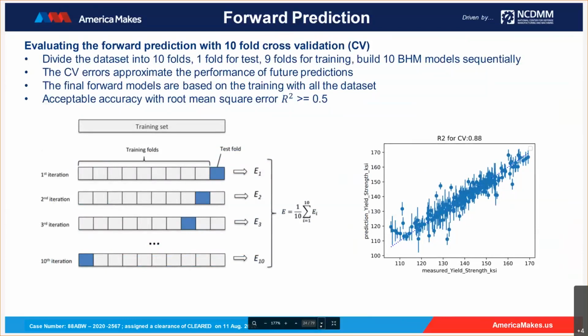After developing our first set of forward prediction models, it's important to validate and estimate the prediction capability. So we are doing the validation in 2 ways. The first way is the popular cross validation process, in which we divide the data into training and testing. In this case, we are dividing the data into 10 folds. 1 fold is selected for testing, and 9 folds are selected for training. Then we iterate this divide and combine technique, developing 10 sets of smaller BHM models in sequence, as shown in the plot. For these 10 sets of BHM, we individually check their prediction accuracy and combine them in the 45-degree plot as shown on the right figure.